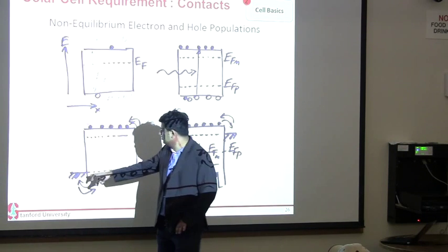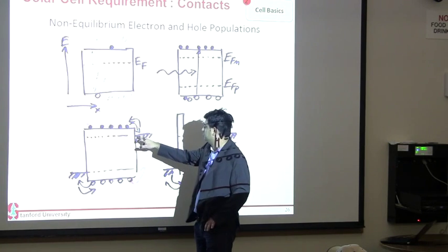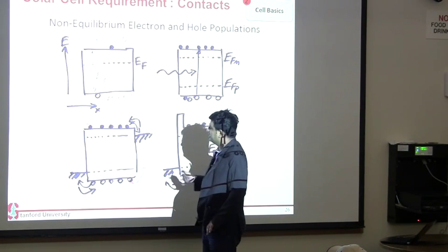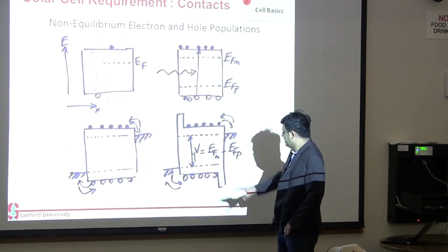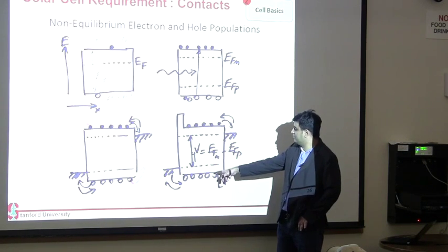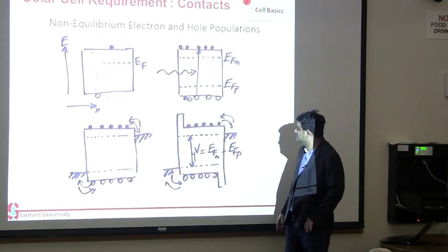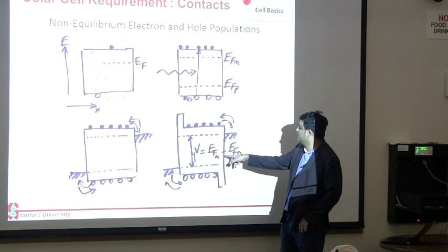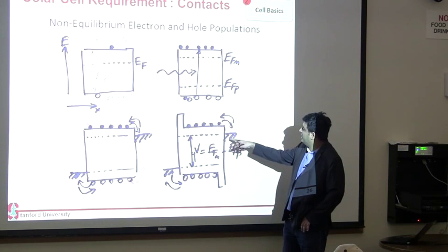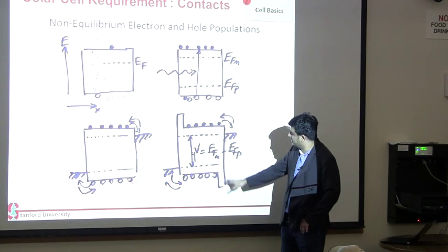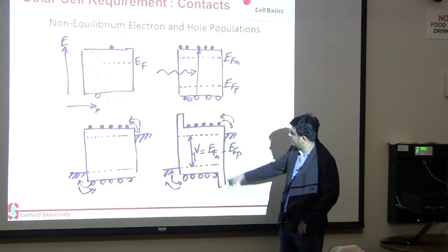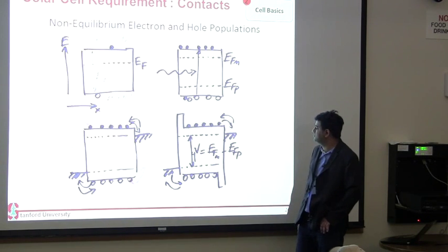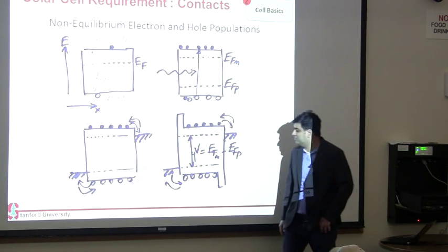I could essentially have two contacts, one being selective to my conduction band, and one being more selective to my valence band, and I'll still get my solar action. I could have a structure like this, and I'll show you an example of a company which makes this cell. These kind of cells are made by Sanyo. It's called a HIT cell, or a heterostructure cell. The way this works is you make selective contacts by growing another layer over here, which has a band lineup like this, and growing another layer which has a band lineup like this. So this contact now becomes selective to electrons, and this contact now becomes selective to holes,